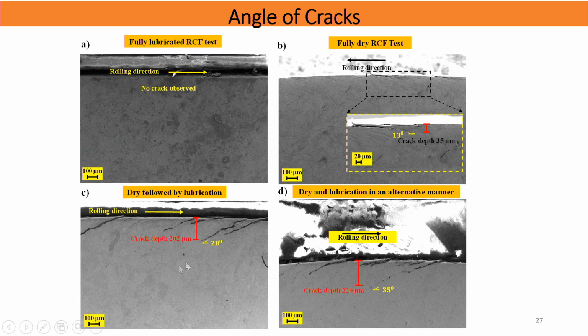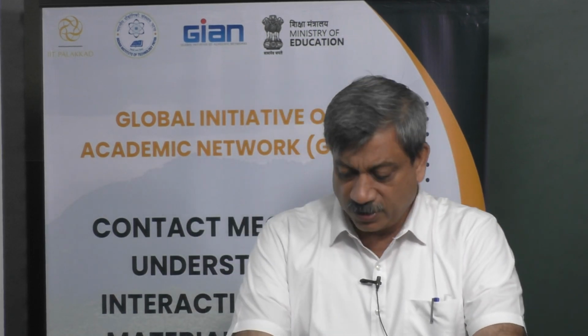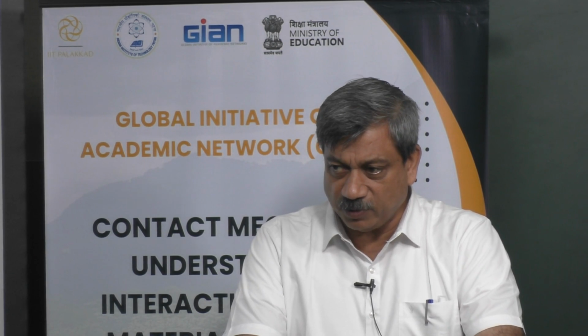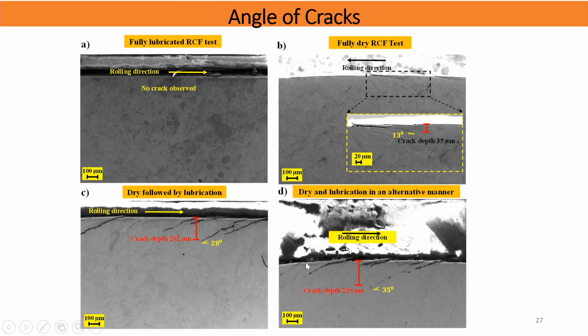So I'll just show you the full dry test. We did a fully lubricated RCF test, a fully dry RCF test, dry followed by lubrication, and dry and lubrication in an alternating way. The lubrication is oil, not water. It is a mineral base oil, ISO VG 30. In this, you can see that the crack formation is very, very strong, and at a very shallow angle, 13 degrees, for the fully dry test. For dry followed by lubrication, the crack angle is about 28 degrees. For dry and lubrication in an alternating way, it is about 35 degrees.